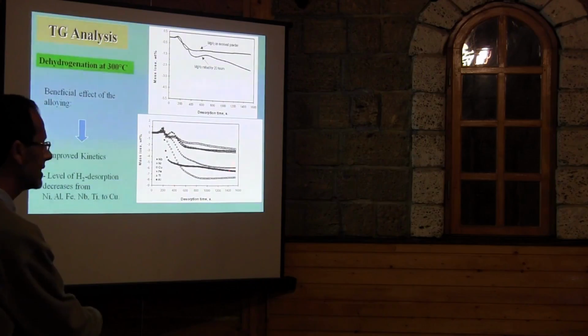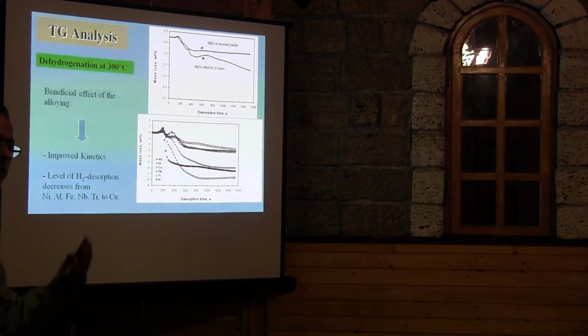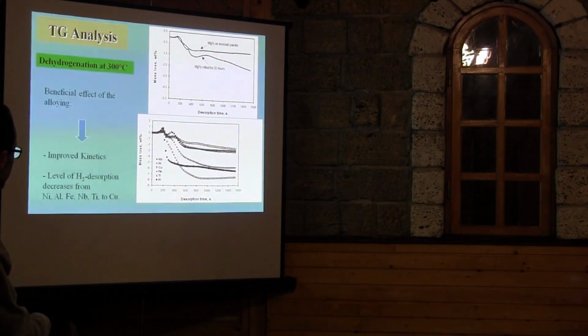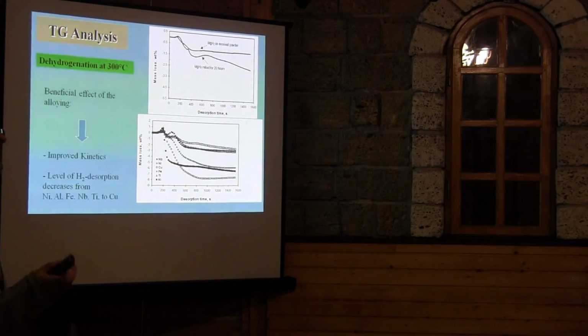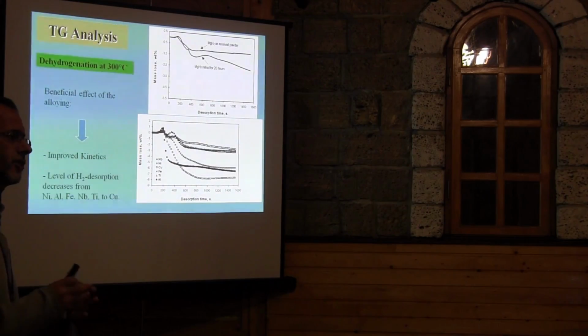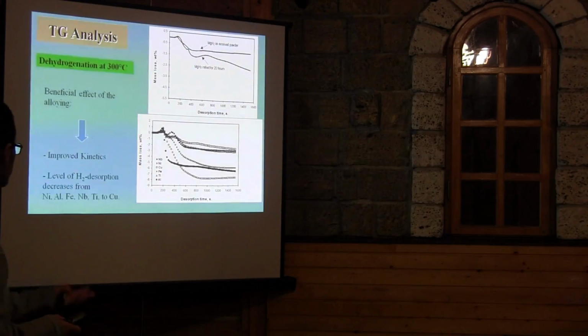Now you can see when I mix with another metal, the kinetics completely change. So which one is the best? Nickel. If you check nickel here, the best element is nickel, so we confirm our theoretical calculation. Also, nickel is well known as a catalyst for hydrogen dissociation. That's why we use it.